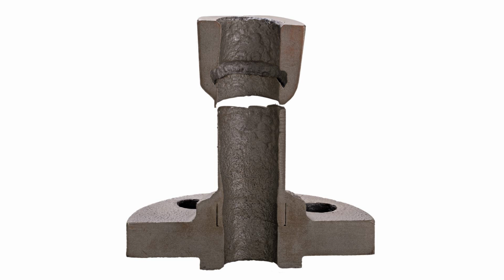The semiconducting form is rich in vanadium pentoxide. At high temperatures or lower availability of oxygen, refractory oxides, vanadium dioxide and vanadium trioxide, form. These do not promote corrosion. However, at conditions most common for burning, vanadium pentoxide gets formed. Together with sodium oxide, vanadates of various composition ratios are formed. Vanadates of composition approximating Na2O·6V2O5 have the highest corrosion rates at temperatures between 593 °C and 816 °C.